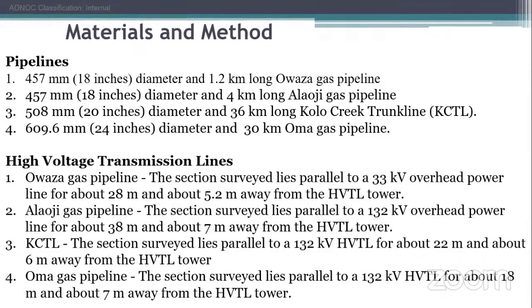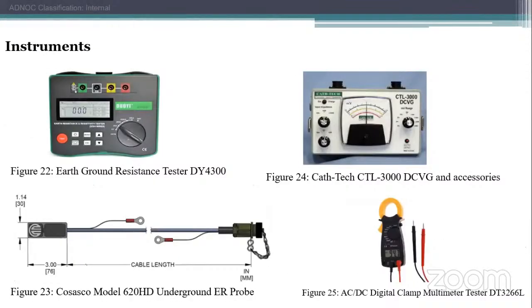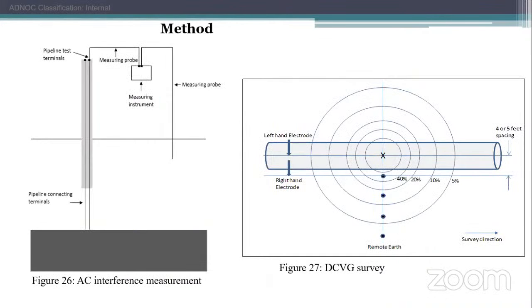The first one paralleled the 33 kV line. The Aloji line was a 132 kV. KCTL also had 132 kV. 4 instruments were used for this study. Figure 22, the ground resistance instrument, was used to check soil resistivity. The Cath-Tech CTL-3000 DCVG was used for coating defects. Another one was used to monitor the coating corrosion, and the other one to measure the level of AC interference.